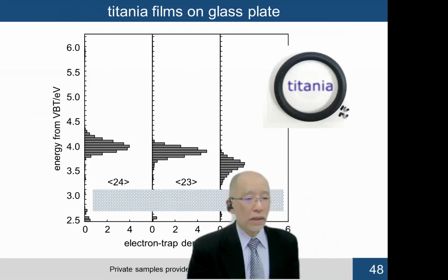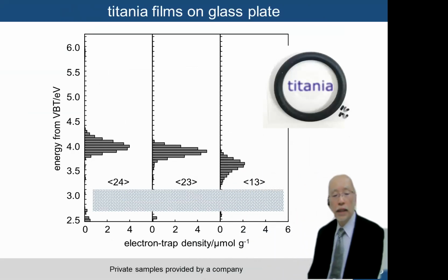And this is the result for a titania thin film, probably about 1 micrometer thick. It is completely transparent. It is almost impossible to take an XRD pattern because of the very small thickness, and also because they are amorphous.